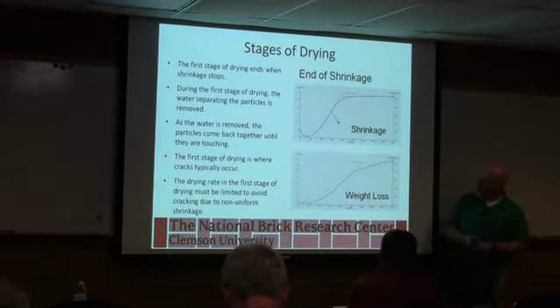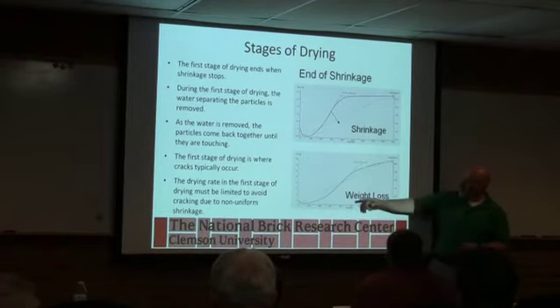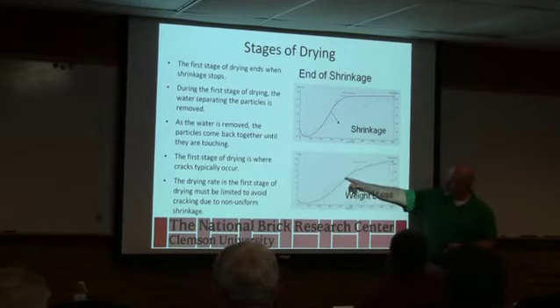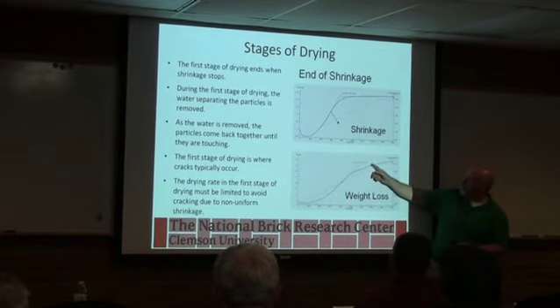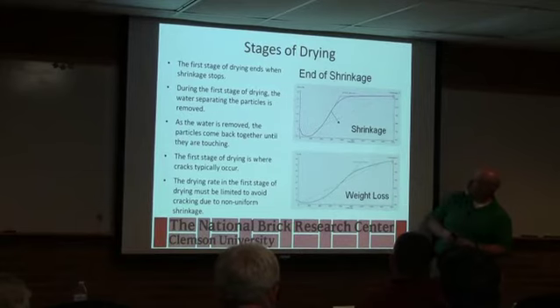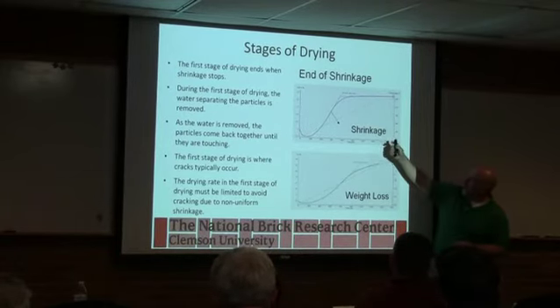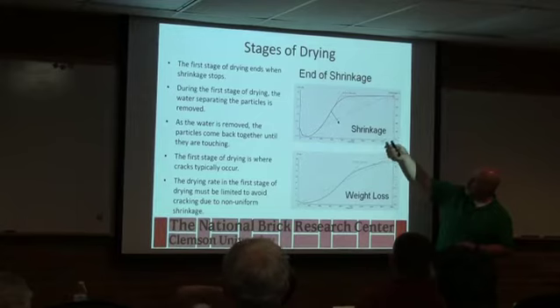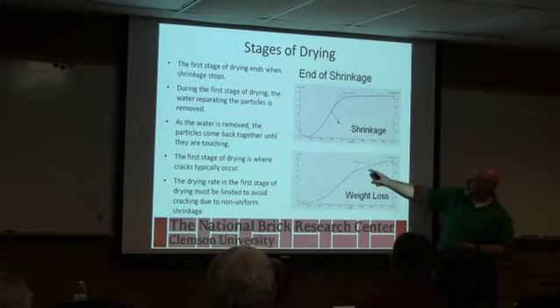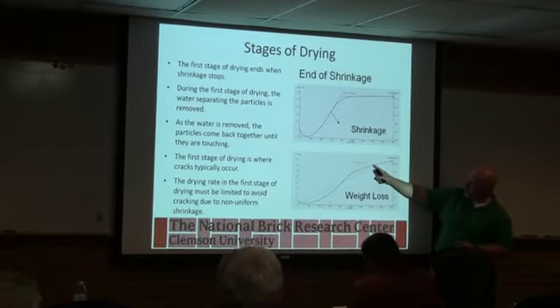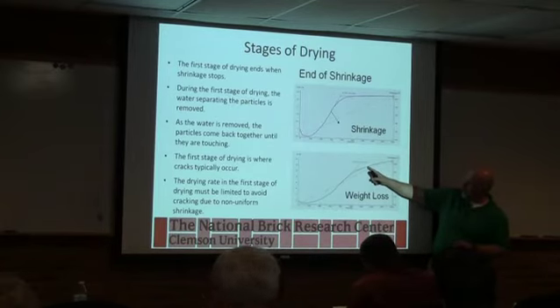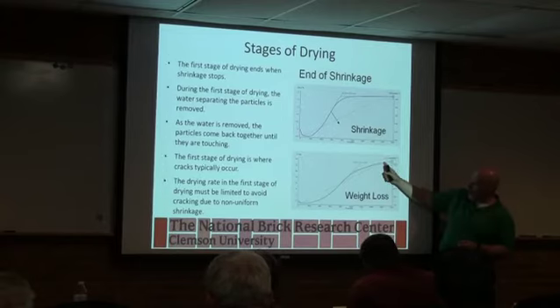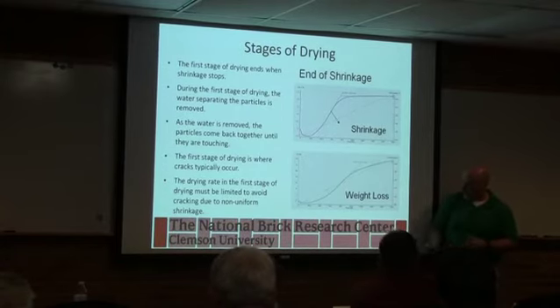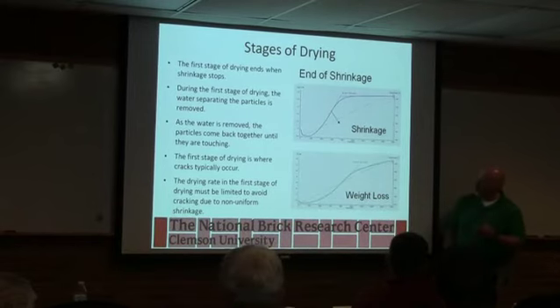So remember we talked about this, it's just plotted a little differently, but we can see where shrinkage is taking place. So this is increasing shrinkage, and then it kind of levels off on us. Or excuse me, that's weight loss. This is shrinkage up here. So we can see that's the end of stage 1 right there. So this would be stage 1, and then this would be stage 2. And this is kind of plotted opposite of what we saw earlier. It's just easier to work with. This is that first declining rate. So this is where we'd be getting into the pore water in the capillary. And then out here we're getting into the hygroscopic water. But this is that forming water we talked about. So you can actually see it on a real brick.